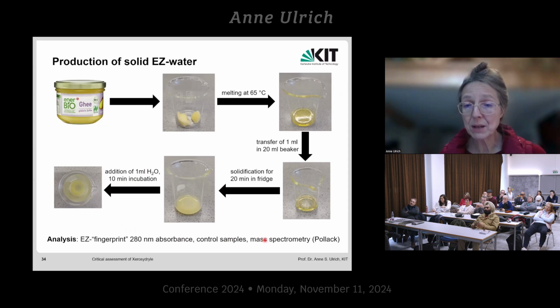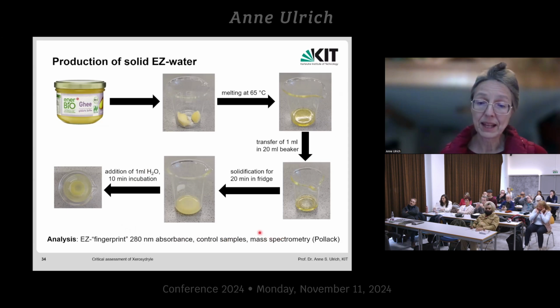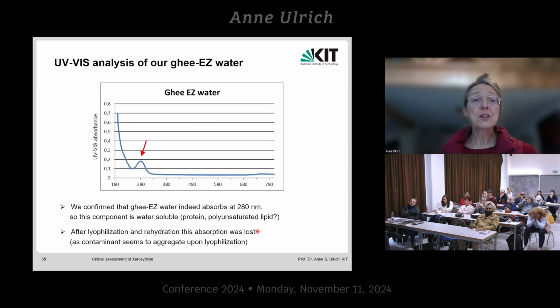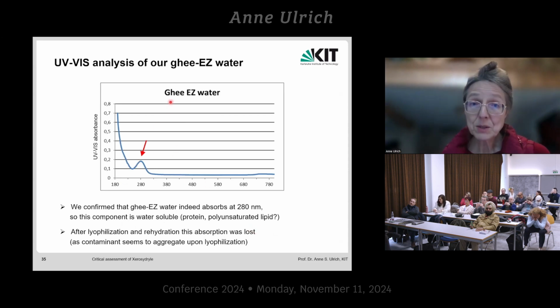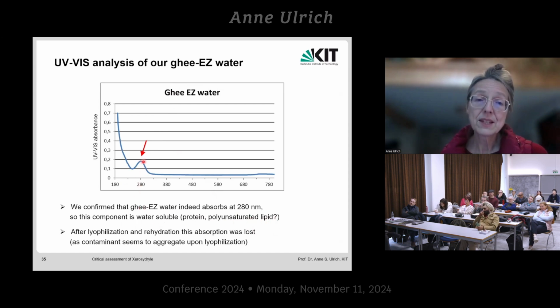And then you check for the absorbance. You can do control samples. You can do mass spectrometry. And that's what we did. So in fact, we could reproduce the liquid water that was siphoned off the ghee surface. It had a massive 280 nanometer peak. Is it protein or is it polyunsaturated lipid? Interestingly, when we lyophilized the samples, this peak became much smaller and was lost.